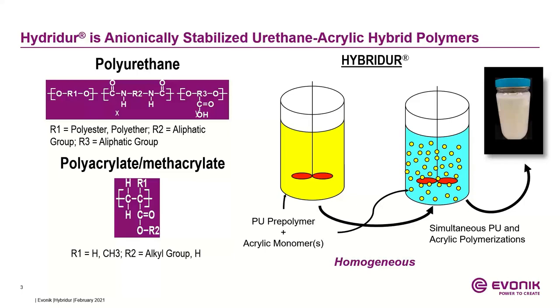The polyurethanes, especially the solvent-borne polyurethane versions, require very high levels of VOC to formulate. The waterborne polyurethane dispersions, on the other hand, require significantly less VOC and are popular for a variety of coatings applications, including wood, leather, metal, concrete, and even composites. The superior physical and mechanical properties of polyurethane dispersions are attributed to a combination of their molecular structure, and it has that hard-soft domain morphology, which is basically responsible for the superior performance.